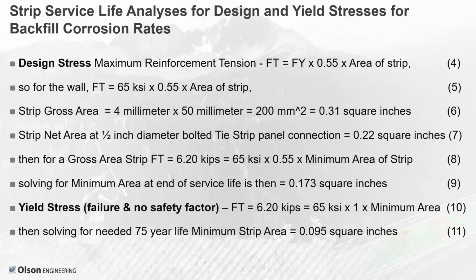But if you apply that as being the most conservative point with the loss of section, et cetera, for a gross area strip yield stress, design stress calculation, you end up with 6.2 kips, which is equal to 65 KSI times the minimum area of the strip. So when you solve for the minimum area at the end of the service life, you would want to have 0.173 square inches left. So it would have dropped from the 0.31 to 0.173, or nominally 55%.